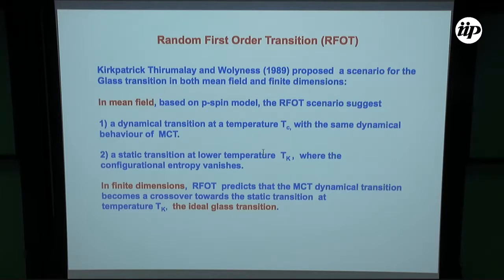And this scenario was proposed for both mean field and finite dimensions. So in mean field, based on the p-spin model, as you heard this morning, the RFOT scenario suggests first a dynamical transition at the temperature Tc with the same dynamical behavior as mode coupling theory. But then below this critical temperature, they propose a static transition, TK, where the configurational entropy vanishes, which corresponds, if you like, to the so-called Kauzmann transition, where the entropy vanishes. So this is more or less the situation in the mean field theory.